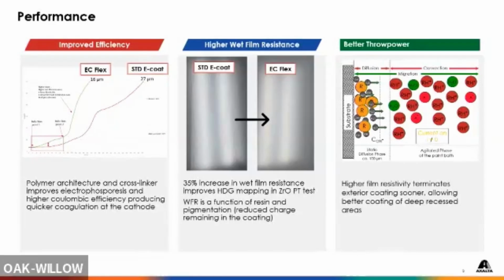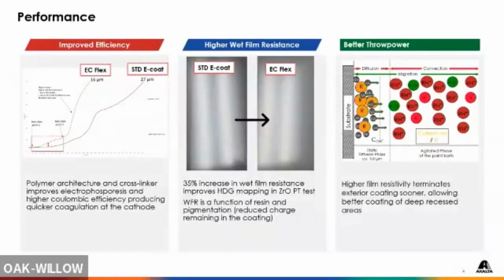In the middle, this is a cool little test we've done. Over the years, as the substrate complexity has changed, as we move from zinc to zirconium oxide pretreatments, we still have to perform over all of these substrates. What we've done in the middle one is we've actually taken pretreat material and poured it over the panels and let it dry, and then applied the coating to it.